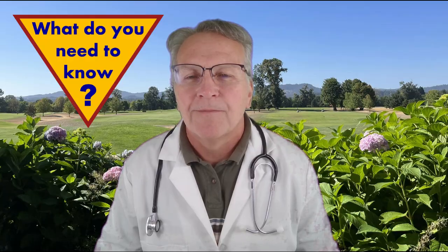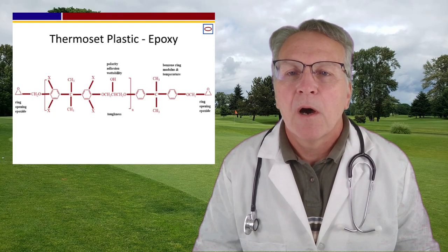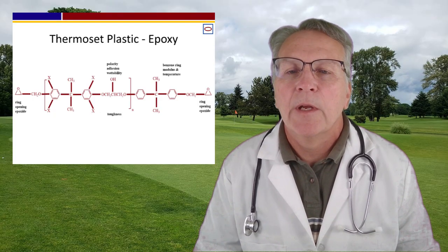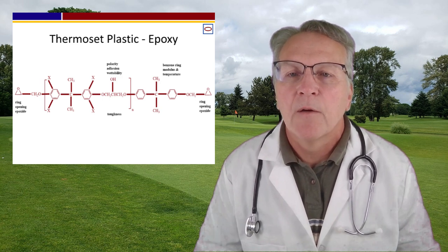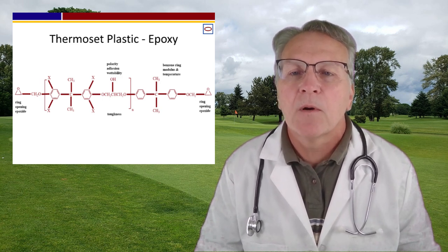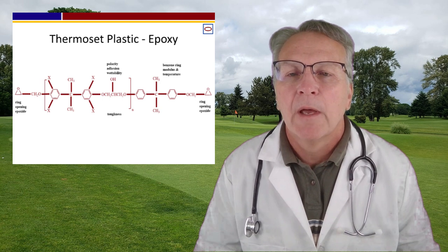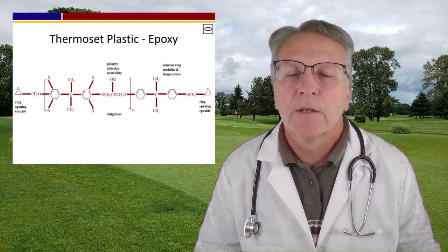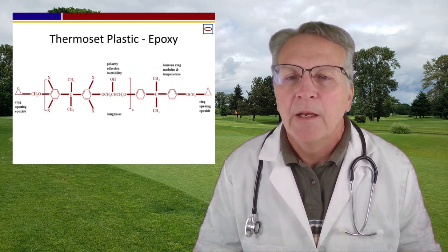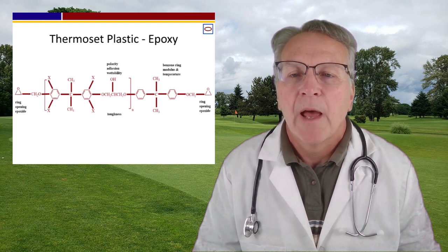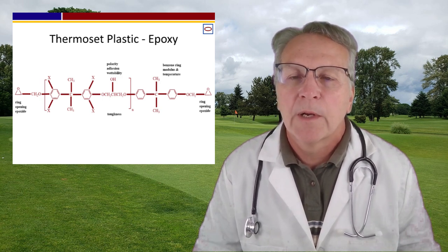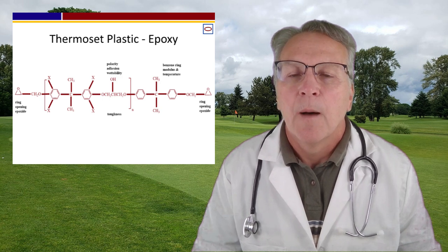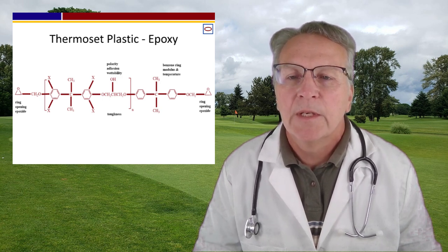Epoxies have a lot going on with their unique chemistry, including condensation polymerization of ring opening epoxides and alcohols to build molecular weight, and benzene rings for high modulus and temperature capabilities, and ether structures for toughness, and alcohols giving polarity for adhesion and wettability. Epoxy molding compounds, or EMCs, can be cross-linked with amines and are highly filled thermoset plastics.